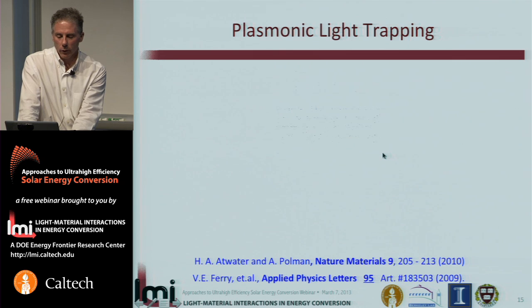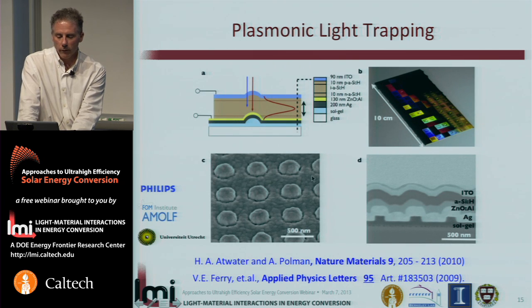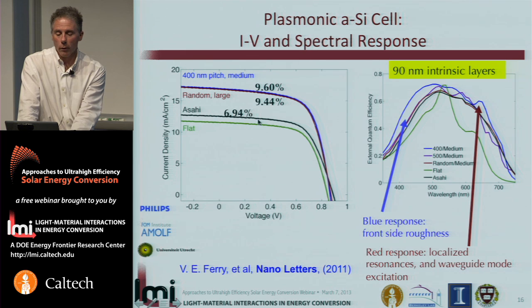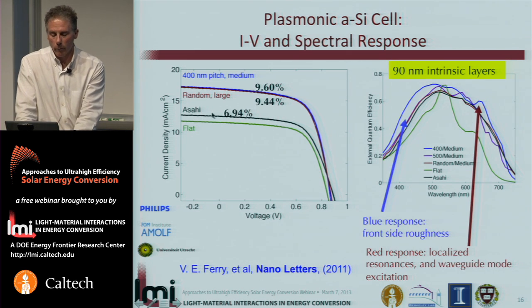And here's an example of such a structure. This is from the work of EFRC researcher Vivian Ferry, also done in collaboration with the group at the AMOLF Institute in the Netherlands, on the fabrication of nanostructured plasmonic back reflectors that act as mode converters. And using a soft imprint patterning technique, it's possible to print these over large areas. And in this case, the photoabsorber is a PIN amorphous silicon solar cell, which is conformally grown on top of this plasmonic back reflector. And what Vivian found was that one can achieve substantial increases in the photocurrent over either a flat back reflector or even a randomly textured back reflector, which for many years was the industry standard for back reflectors in thin film solar cells.